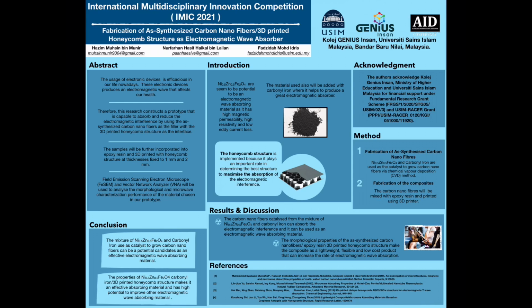The mixture of sintered nickel, zinc ferrite and carbonyl iron are used as the catalyst to grow carbon nanofibers via chemical vapor deposition (CVD) method. The samples will be further incorporated into epoxy resin and 3D printed with honeycomb structure at thicknesses fixed to 1 mm and 2 mm. The epoxy resin base will be printed in honeycomb structure to maximize the absorption of electromagnetic wave by having multiple reflection in the sample.